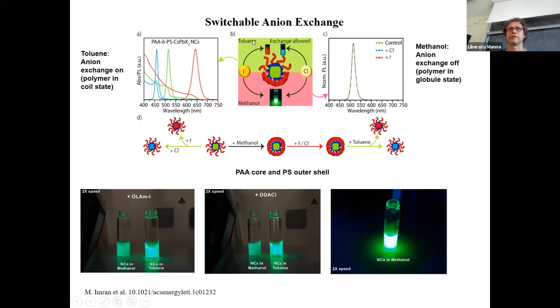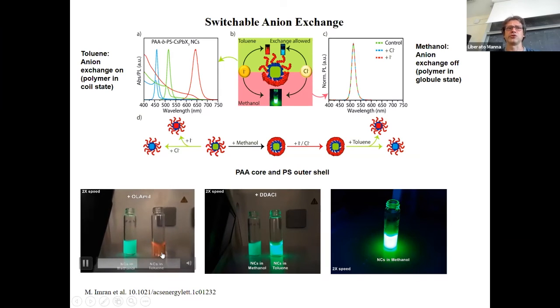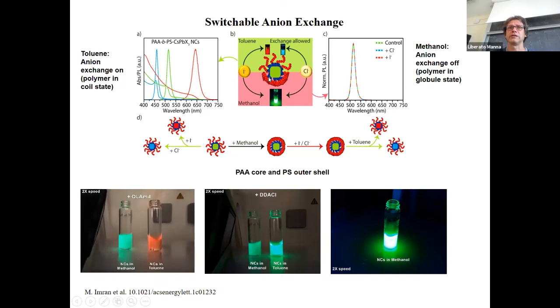And now comes the interesting thing: depending on whether the solvent in which these polymer-encased nanocrystals are dispersed is, for example, toluene, relatively non-polar, or methanol, you can switch anion exchange on or off. So for example, in toluene, you can take nanocrystals and add, for example, iodine precursors, and immediately the anion exchange gets triggered. Whereas when they are in methanol, the anion exchange is completely suppressed. This is because in one case, the outer shell is in a globule state, and so it makes the core inaccessible to the anions. In the other case, the polymer is in the coil state, and so the nanocrystals are accessible.